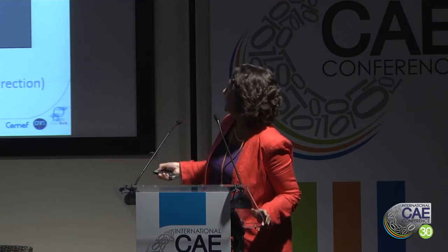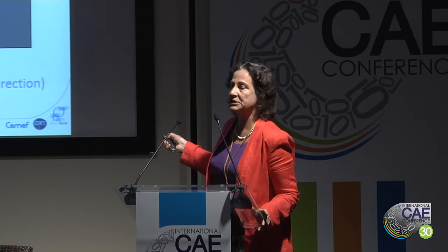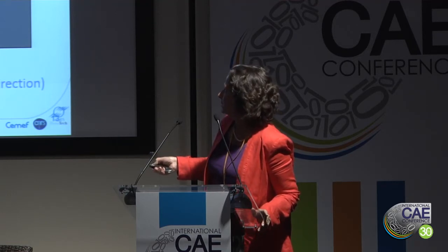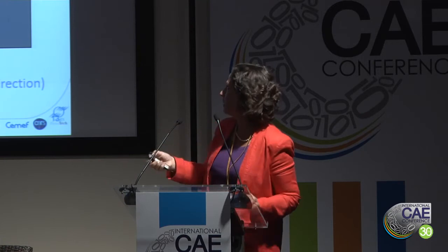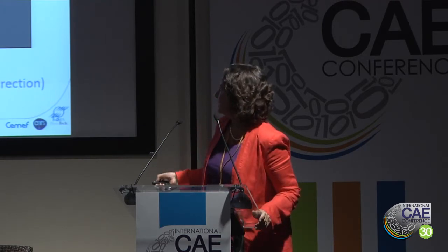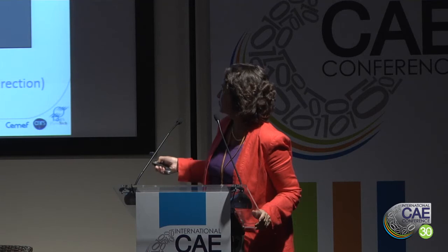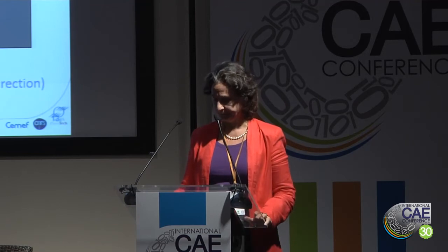It's only interface debonding. The other is the fragmentation. For the fragmentation, we have this kind of inclusion here. So remember, this is the image here. We have the inclusion here, the matrix, and a stress is applied. And when the stress reaches this threshold, the maximum principal stress, we have this failure on a specific plane.